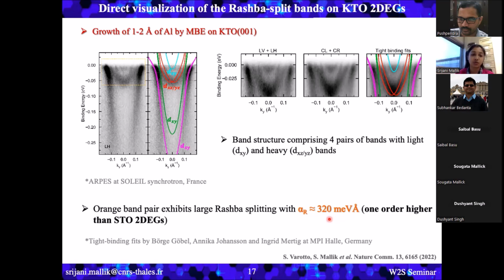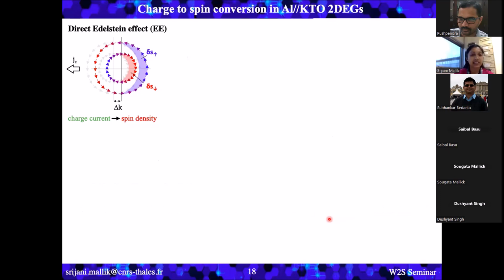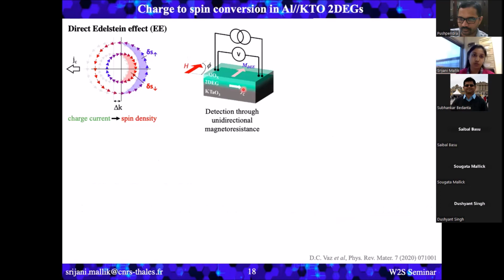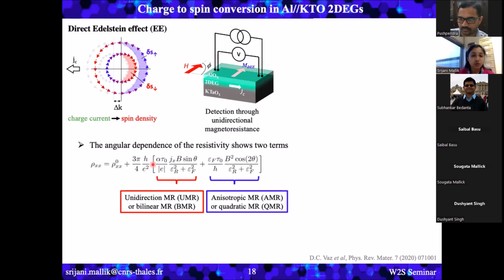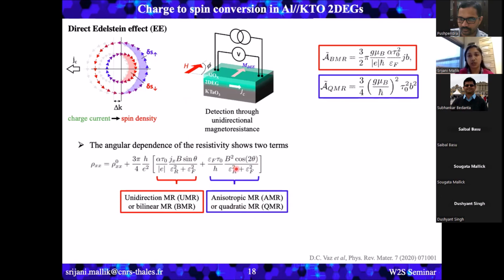Of course, we wanted to measure it experimentally. To do so, we took advantage of the direct Edelstein effect, that is, charge to spin conversion. In our sample, we pass a charge current, and due to the direct Edelstein effect, a spin density gets generated perpendicular to the charge current direction. Now if we rotate our sample in plane with respect to the magnetic field direction, then the resistivity equation should look like this, where there should be 2 theta dependent terms. The first one is known as bilinear magnetoresistance, and this varies as sin theta, whereas the second term varies as cos 2 theta, and it's known as the quadratic magnetoresistance term. If we look at the coefficients of these 2 terms, the coefficient of BMR varies linearly with the current density as well as the magnetic field, and the coefficient of QMR varies quadratically with respect to the magnetic field.